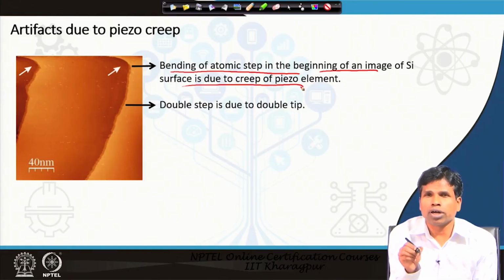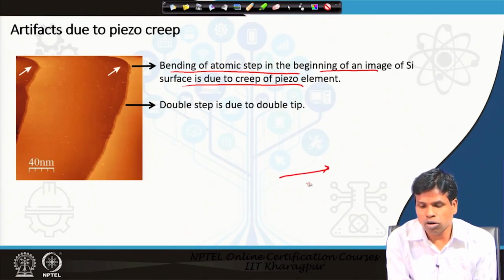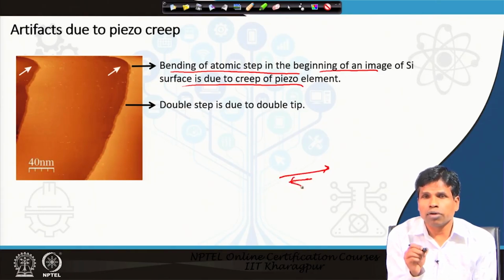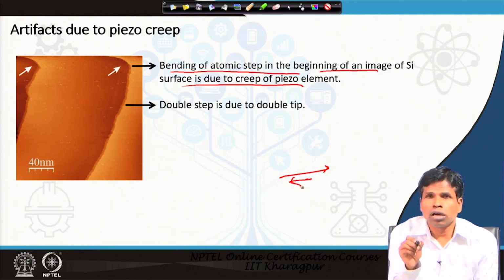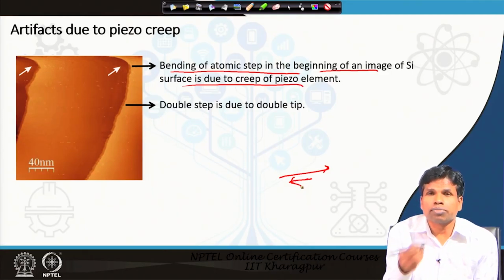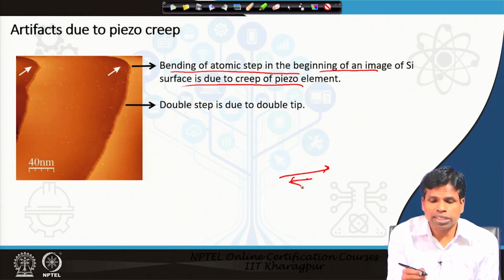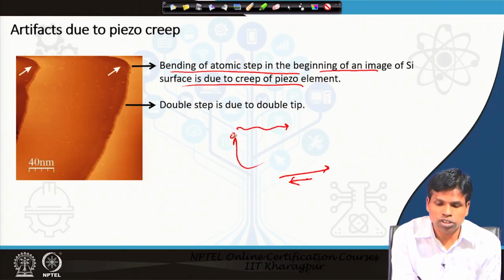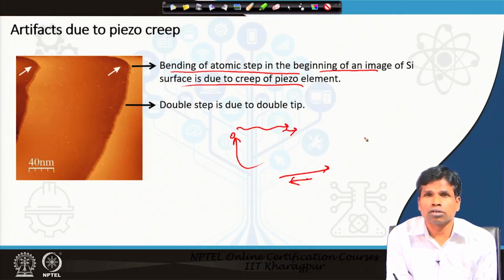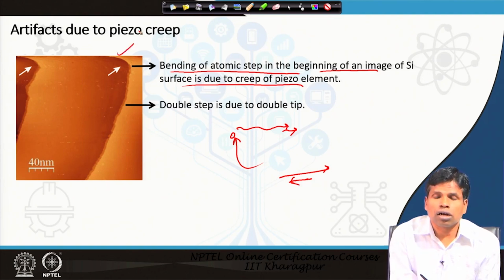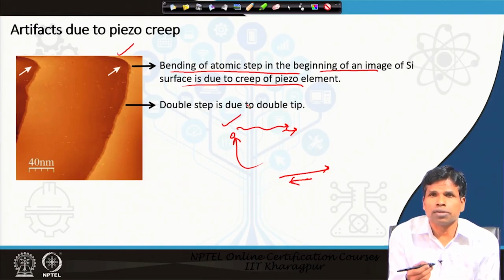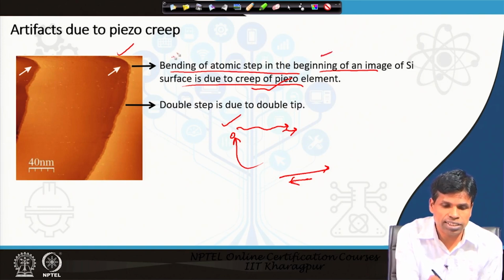Into the piezoelectric scanner we provide the voltage, and when we provide the voltage, it will expand or contract. Now, if we are applying the positive potential, the tip has to move, expanding, and when we bring back the voltage, the tip should contract quickly, but it cannot be done. It never acts instantaneously. It takes time. It is a time dependent phenomenon. So, by the time our voltage has come back to the original position, my tip will still be moving in the other direction, and that leads to this bending. The piezoelectric scanner does not react instantaneously, but takes time, and that leads to creep, or distortion of the image, and in these cases bending is occurring.